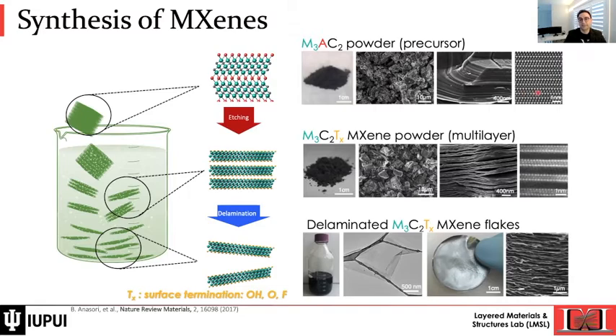And this is how the MAX looks. We have a high-resolution SEM image showing the layered structure, but not a 2D material. Then by removing the A layers, we end up with this exfoliated structure, and you see that we have this open structure between the layers. Now they are bonded by van der Waals bonds or hydrogen bonds. Then by mechanical agitation, sonication, we can break these flakes into single flakes and have MXene solutions.